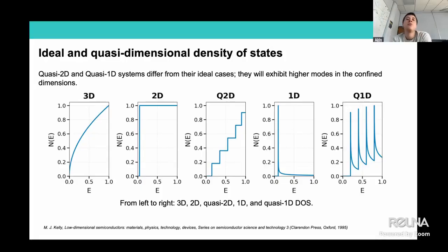What is important here is that most of the systems that experiments will be looking at, and some of the simulations I will show, are actually quasi one-dimensional systems. So an ideal system would have some form of confinement that is transverse to the direction of motion. And if that confinement confines the system in the ground state only, then we can talk about an ideal system. But once we relax that confinement and we can get the higher eigenvalues, the higher modes, into the system, then I would say that that's a quasi low dimensional system. So quasi two-dimensional, quasi one-dimensional system.